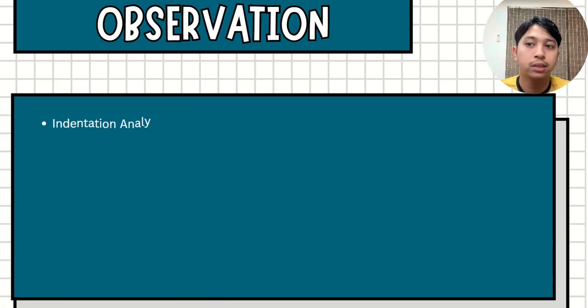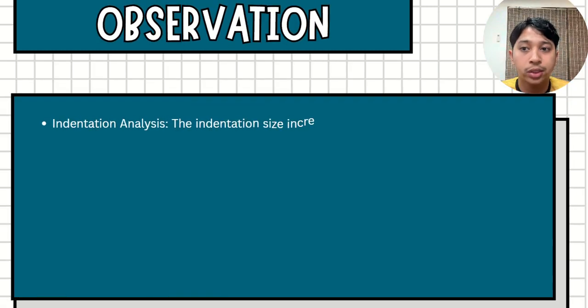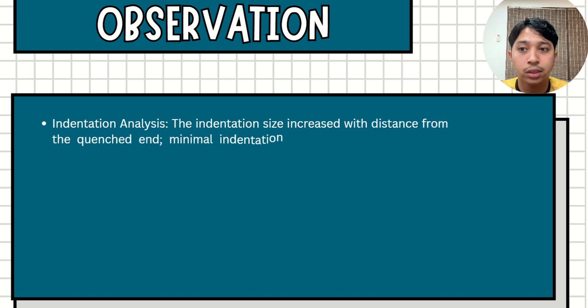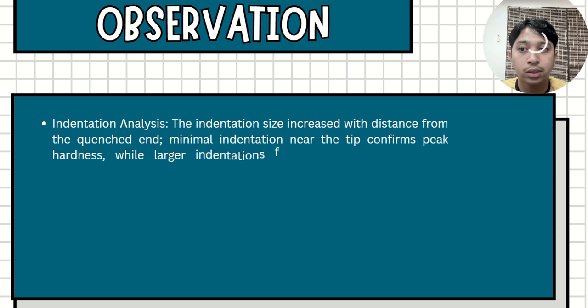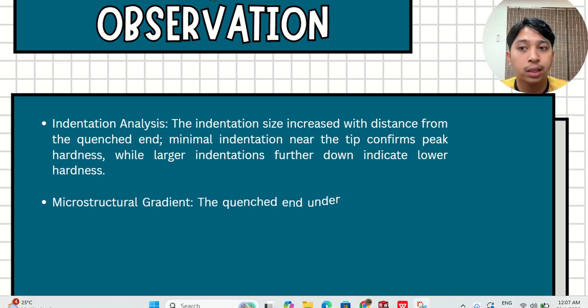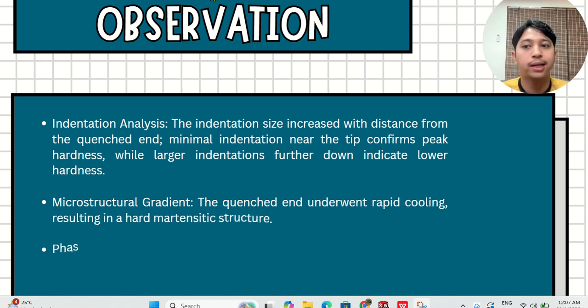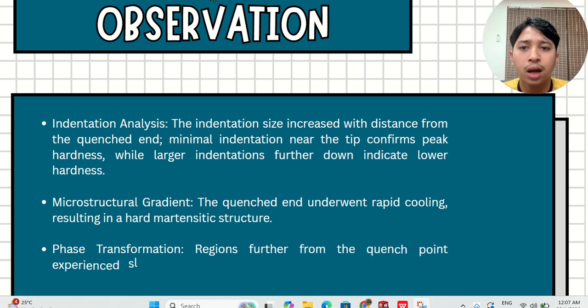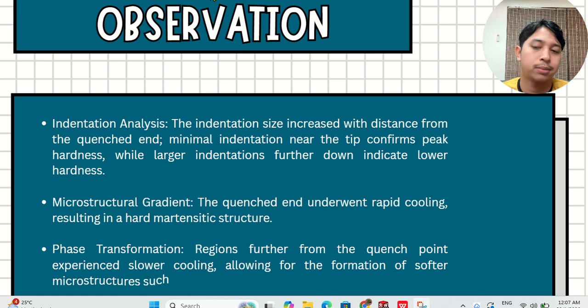In the indentation analysis, the indentation size increases as the distance from the quench end increases. Near the quench end tip, the indentations are minimal, indicating the material's peak hardness. Further away from the quench end, larger indentations are observed, reflecting the gradual decrease in hardness along the specimen.